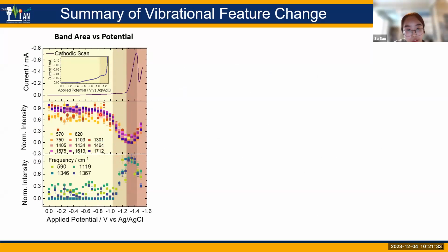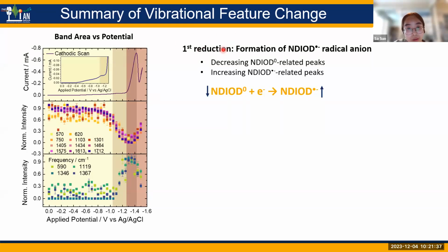So if we think more about this trend, for example, for the first reduction, what is happening, as predicted by previous literature, is the formation of the radical ion of N2200. So basically the neutral N2200 experiences a one electron reduction to form the radical ion. So it's pretty natural to think that the neutral N2200 intensity will decrease. Meanwhile, the polaron-related peak will increase. And this is sort of what we saw here. So we think this group of peaks is related to the neutral N2200 with decreasing intensity when the monopolaron appears. And meanwhile, these four peaks should be related to the monopolaron, which is the radical ion, with increasing peak intensity with more negative applied potential.